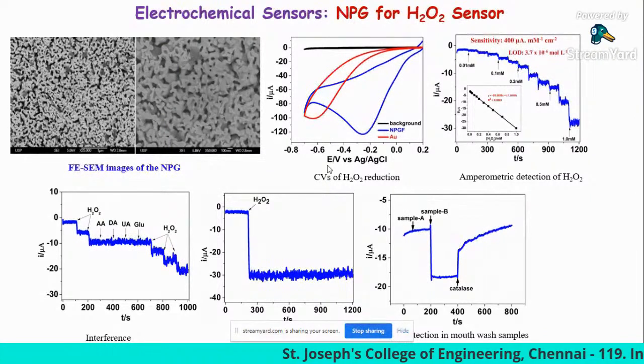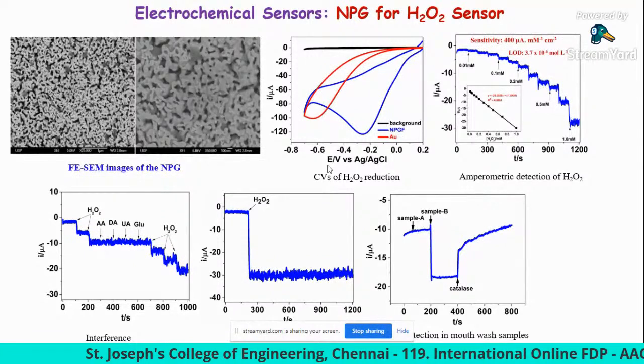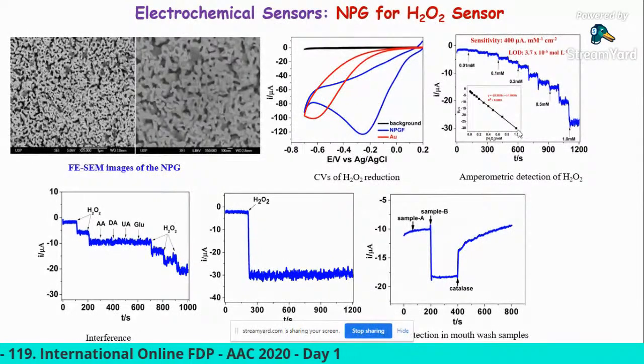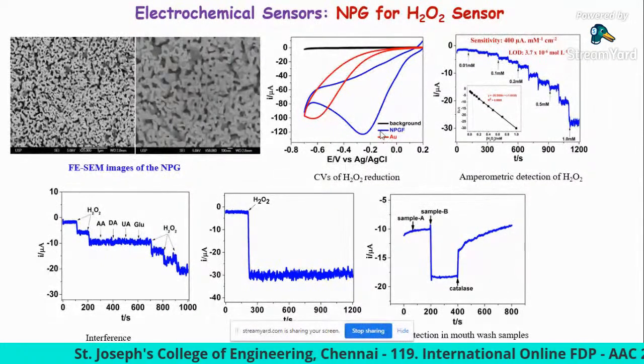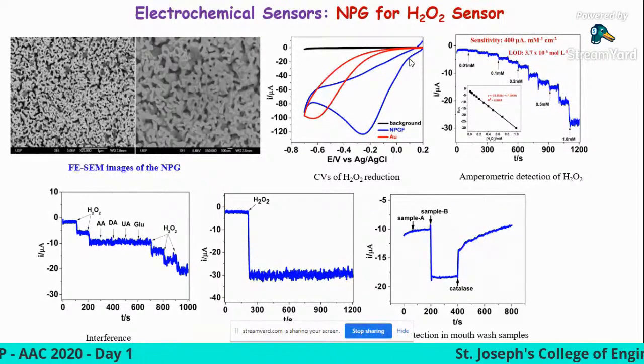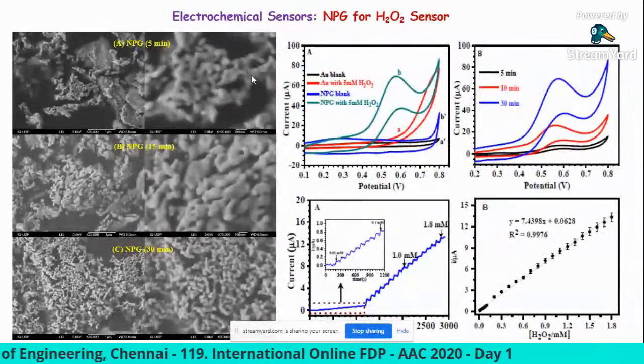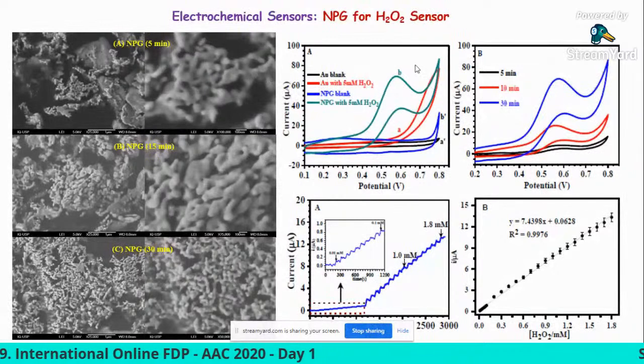Then we thought, why don't we try the hydrogen peroxide oxidation on the anodic side? That means instead of hydrogen peroxide reduction, we tried hydrogen peroxide oxidation, because oxygen is not able to oxidize. Oxygen is always reduced, it will not oxidize. But hydrogen peroxide can be oxidized as well as reduced. So if you study the hydrogen peroxide oxidation, then we can easily overcome the oxygen interference. That's why we started the experiments for hydrogen peroxide oxidation reactions.